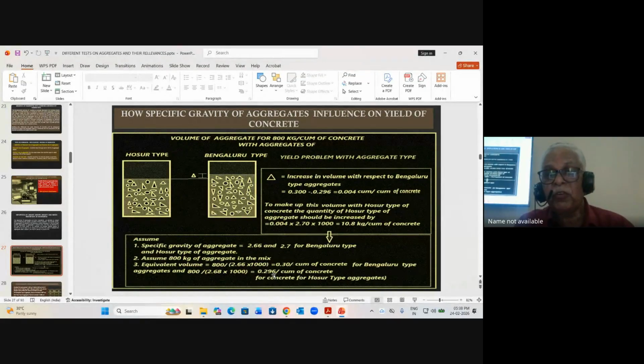0.296 cubic meter is the volume of Hosur aggregate, and 0.3 cubic meter is the volume of Bangalore aggregate. So the difference in volume is about 0.004 cubic meter per cubic meter of concrete. So by just changing our Hosur type to Bangalore type aggregates, there can be a volume difference of 0.004 cubic meter per cubic meter.